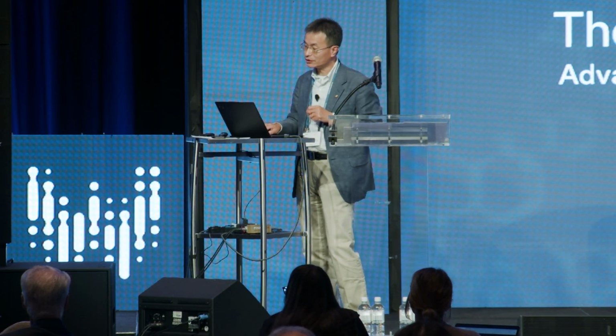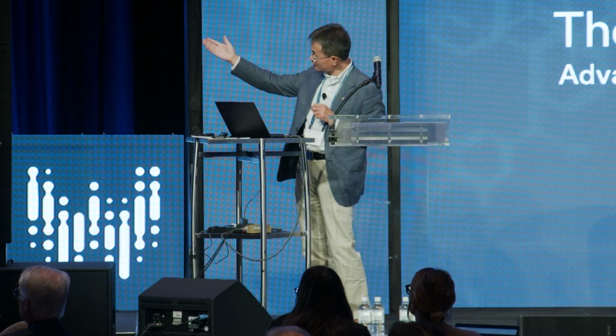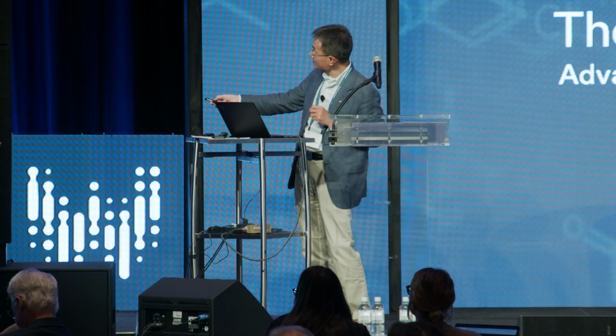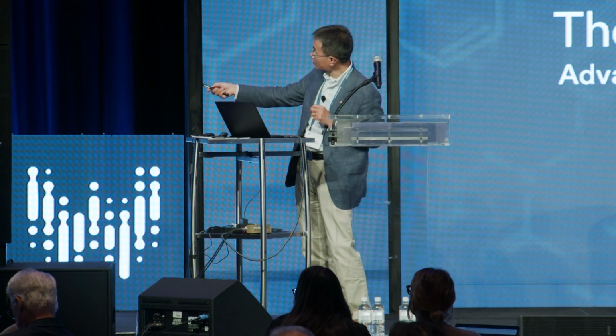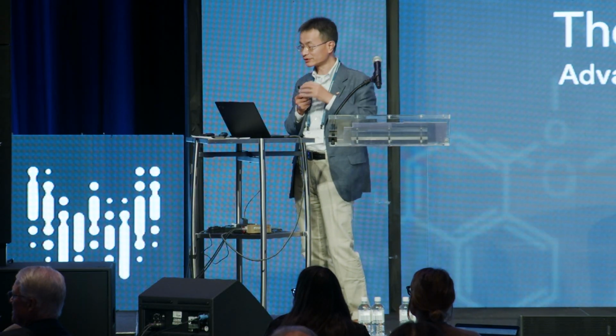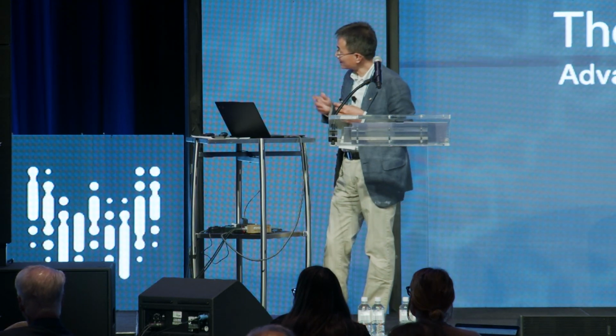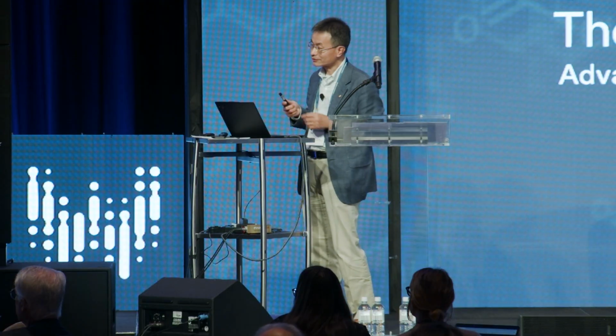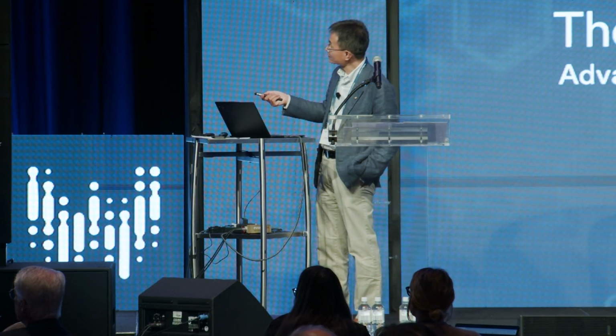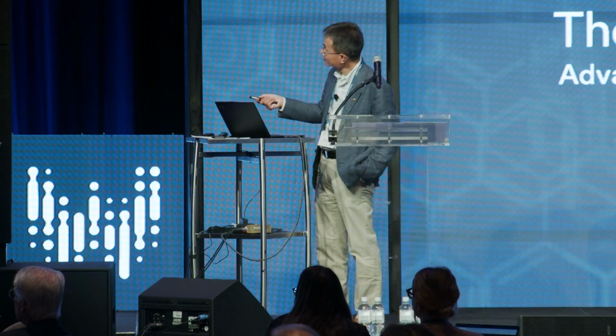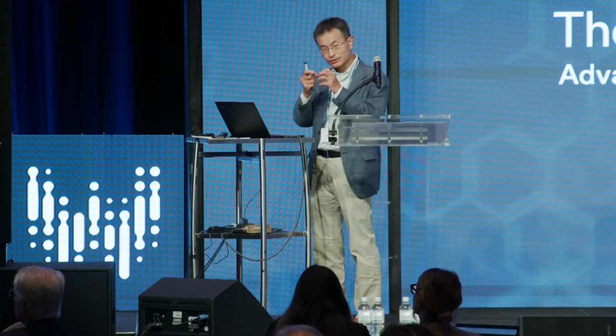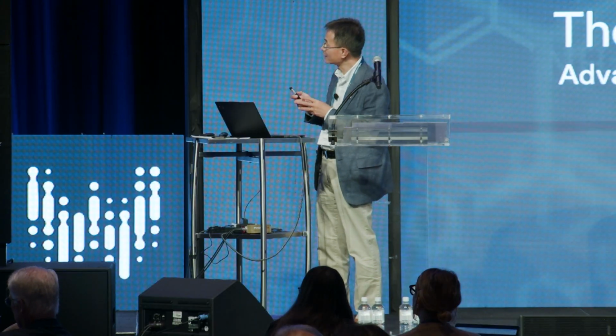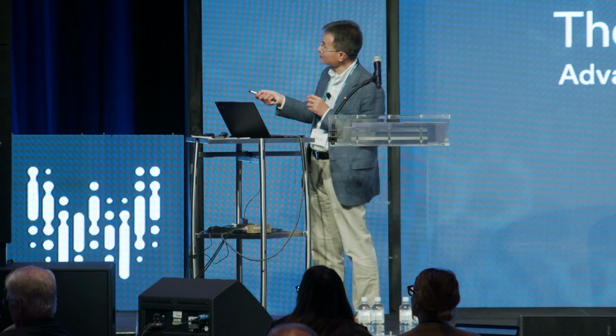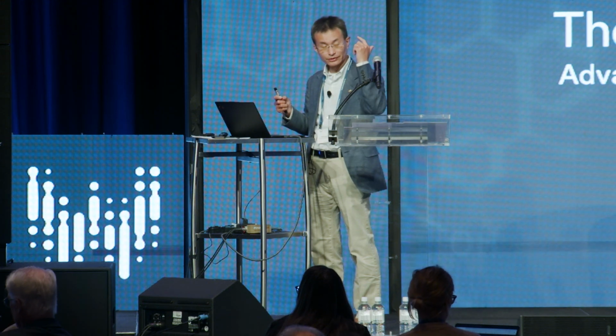But meantime, that offers new opportunities, of course. In the vertical junction, you can further put in a silicon germanium longitudinal junction. That's another way to block the phonon transport, so you can drive the thermal conductivity further down. Why do we want to drive the thermal conductivity down? That again relates to thermoelectrics. Eventually, we figured out a way to do larger-scale production with these silicon nanowires. With this phonon engineering through nanoscopic dimensionality, the ZT of silicon nanowires can be enhanced 100-fold compared to bulk silicon.